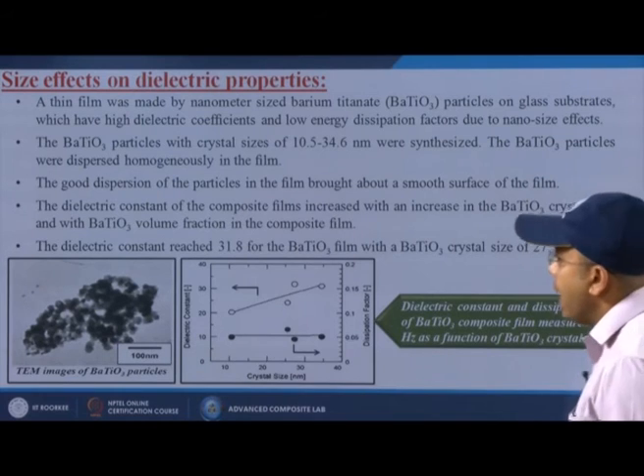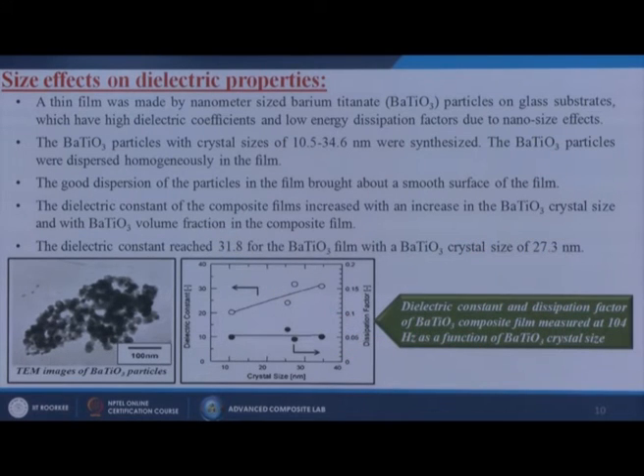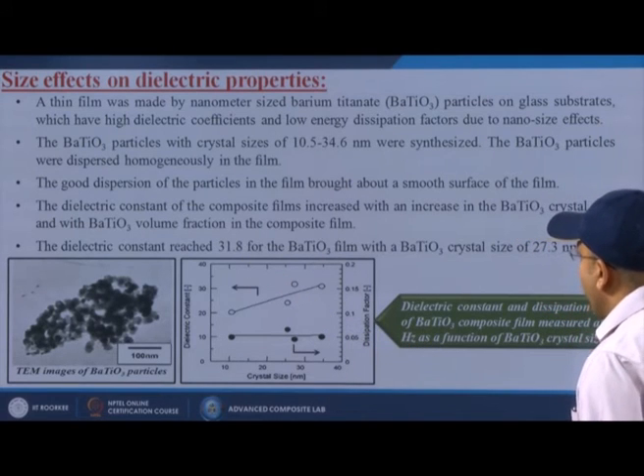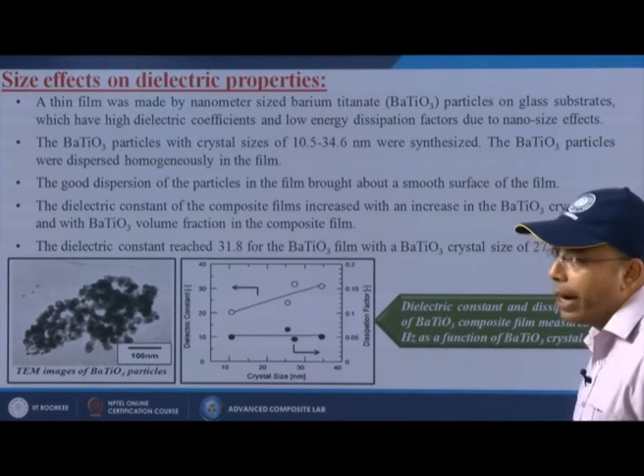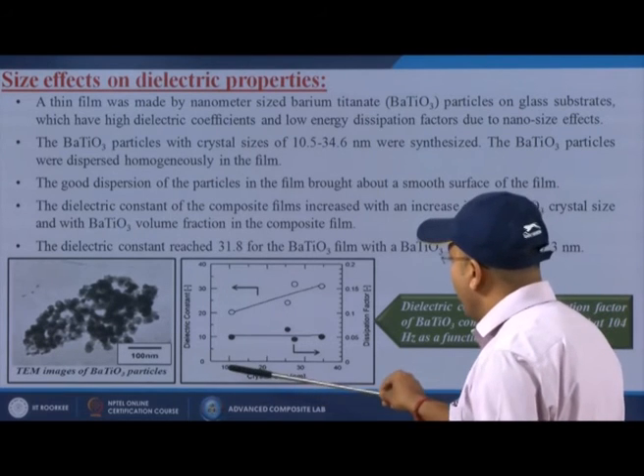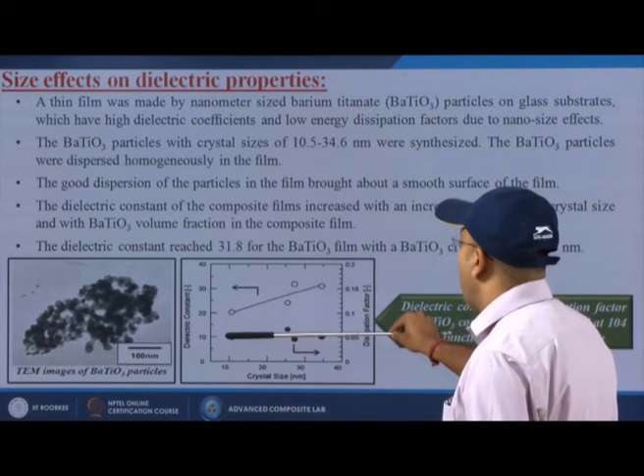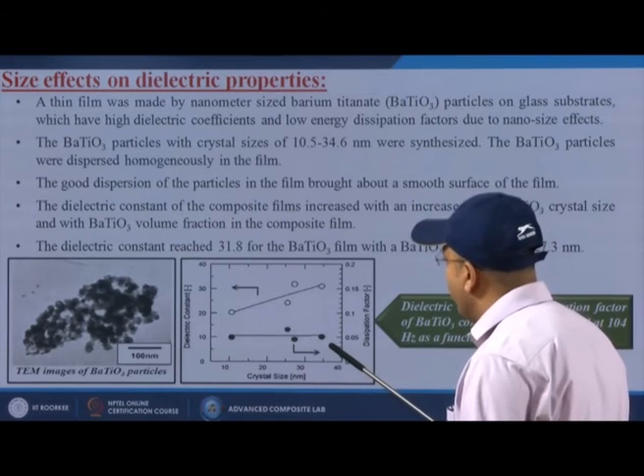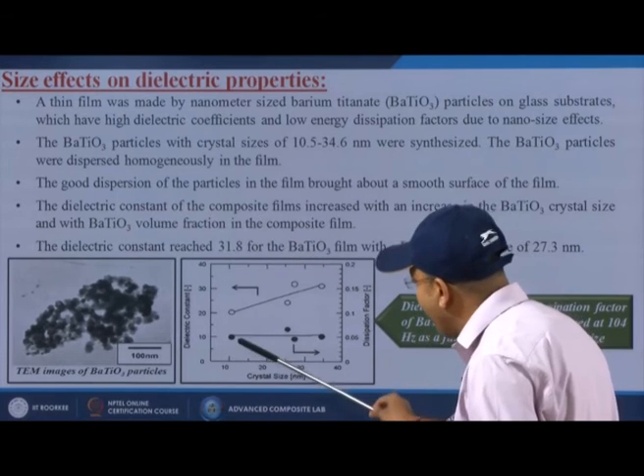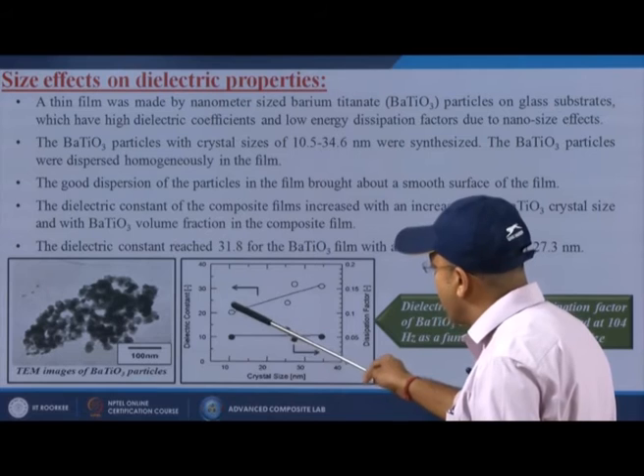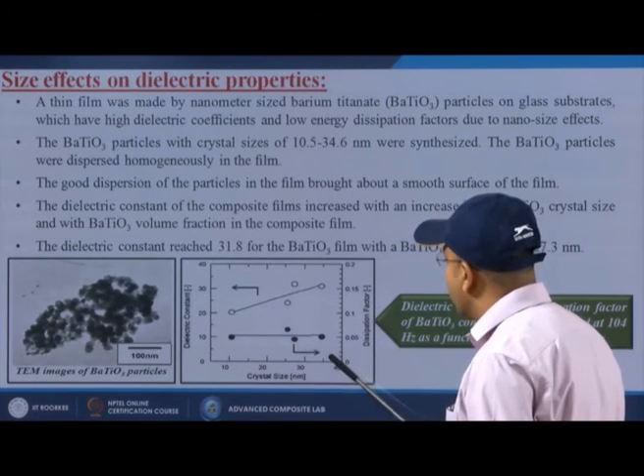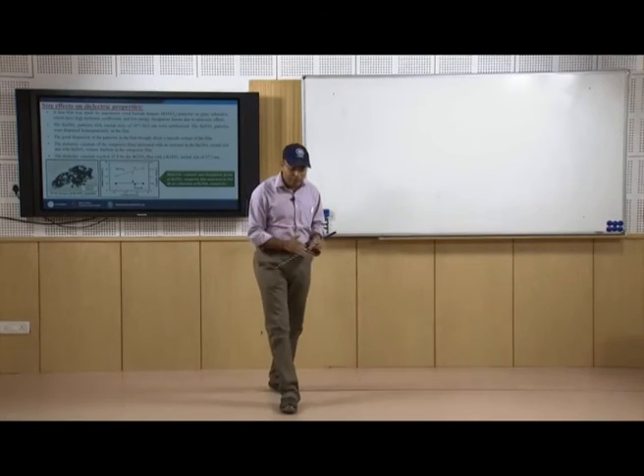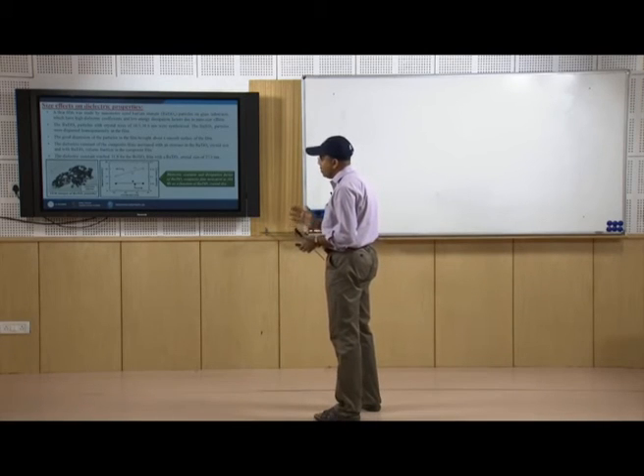The good dispersion we achieved in the film brought about a smooth surface of the film. The dielectric constant of the composite films increased with an increase in the barium titanate crystal size and with barium titanate volume fraction in the composite film. The dielectric constant reached 31.8 for the barium titanate film with a crystal size of 27.3 nanometer. So in this case we can see that when we increase the crystal size, the dissipation factor is not changing, or changes only by a very minimal value, but the dielectric constant is rapidly changing with the increasing crystal size. When the crystal size was around 10, the dielectric constant was almost 20, but when it reached 35, its value also went up to 30. So the increase in particle size clearly reflects that the dielectric constant of that material is changing.